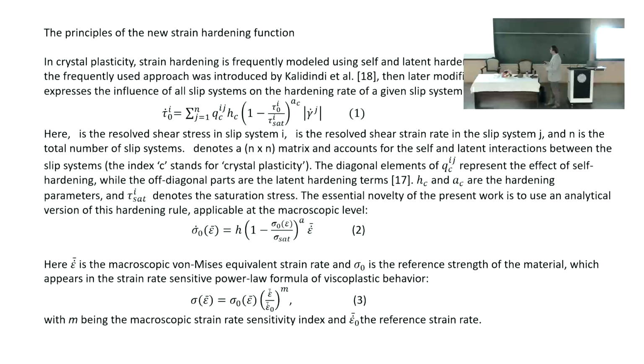That's a very suitable way to describe how the resistance to slip from dislocations increases in a given slip system of a crystal, even the polycrystal, during plastic strain. The parameter here is the slip rate, the shear slip rate in a slip system. We know it from the mechanics equations, by imposing strain on the material. We can calculate, it's complex, but that's another course, how to get the slip distribution in a crystal — it's a rate, of course, a slip rate.